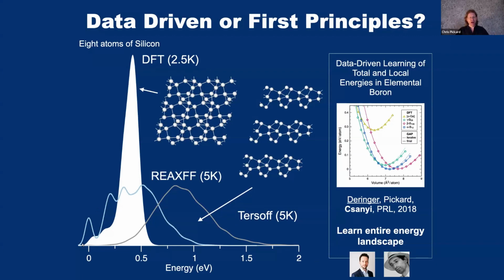What I'm showing are the density of structure states, so the energies of the randomly sampled structures when relaxed using a Tersoff potential and density functional theory. You can see the distribution of energies are just different. That tells you that the energy landscapes are just different. So away from the ground state, the rest of the energy landscape doesn't look like the true ground state, which is probably closer to the DFT result.